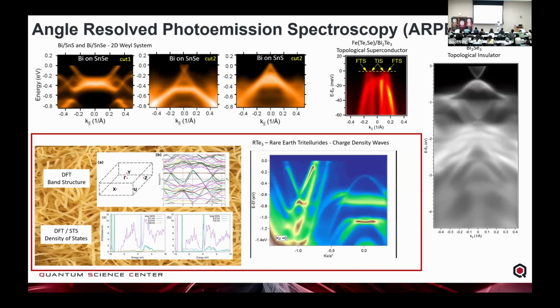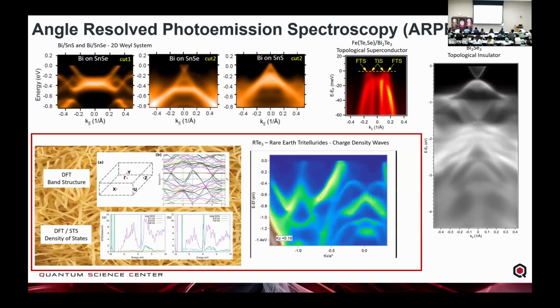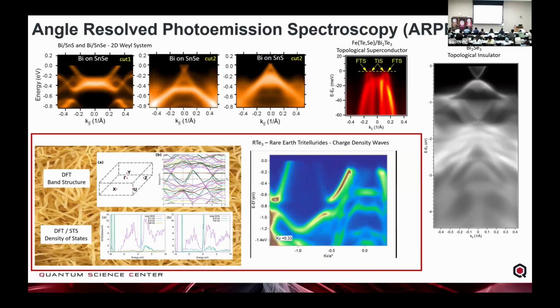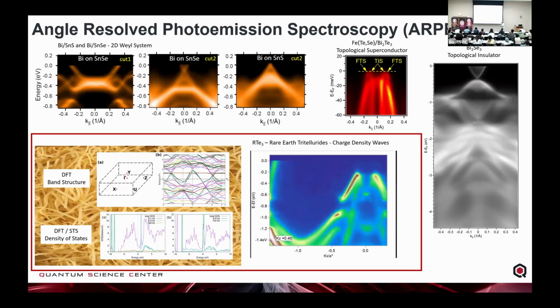So, we can see in theory, we see these spaghetti plots where we're looking at the electronic structure. And so this is directly what we are probing in our ARPES here. So this is a charge density wave material where we're looking at different slices as we see how the electronic structure evolves, and we're directly probing it.